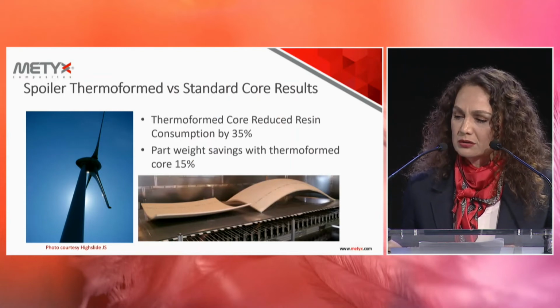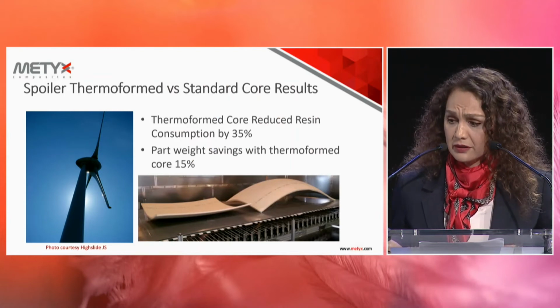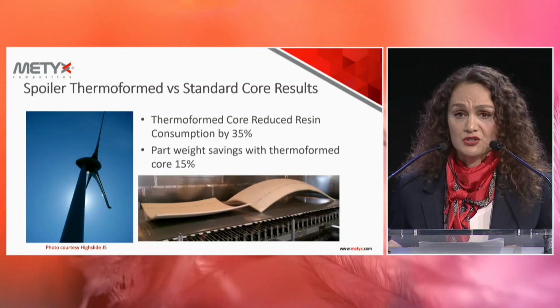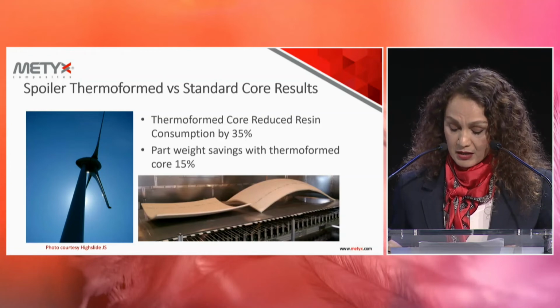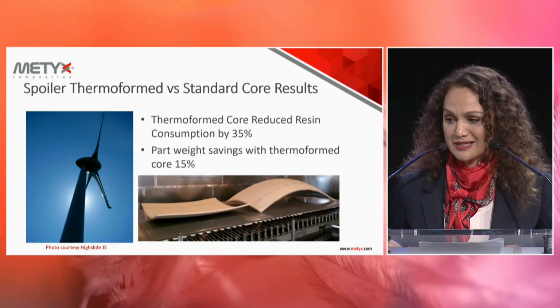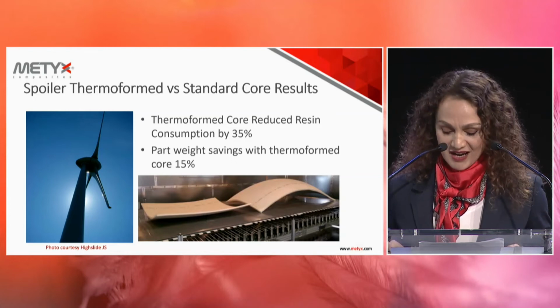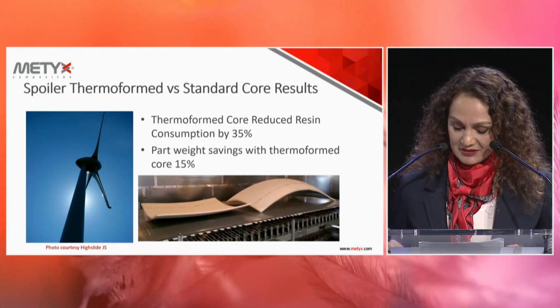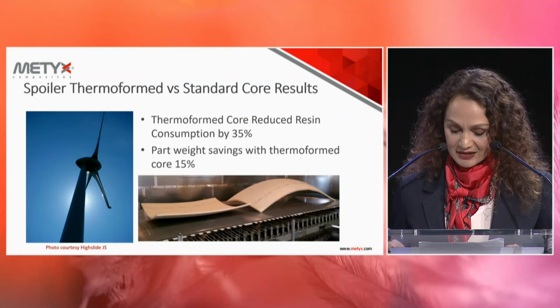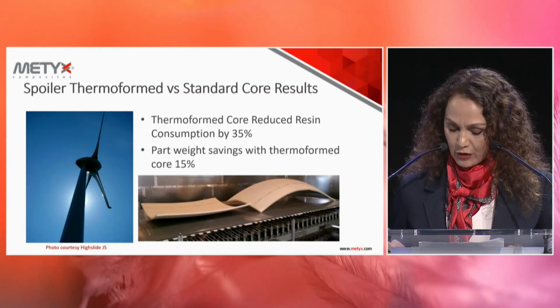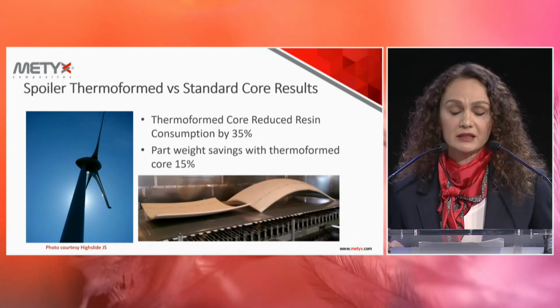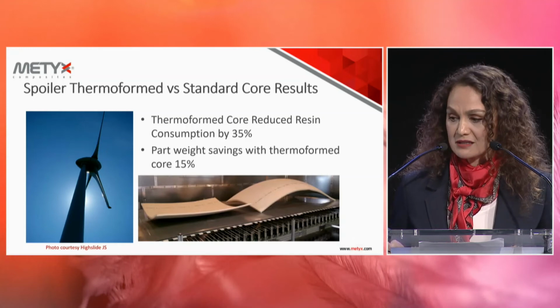The thermoformed core was able to reduce the resin consumption by 35%, which is huge. Considering the resin prices these days, we have to look at that. So part weight savings with the thermoformed core is about 15%, so you are saving building material costs and the part weight associated with that.